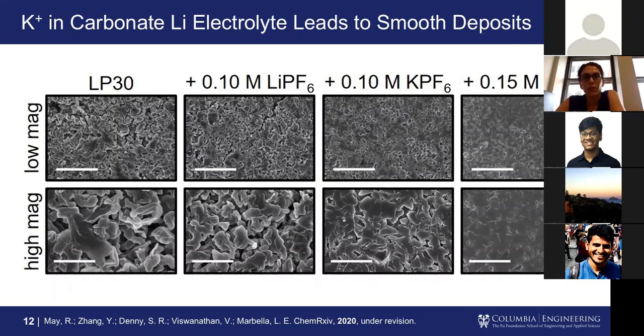So one of the first projects that we started to work on in my lab is, are there some type of additive that we can put into just a conventional commercial carbonate electrolyte that would give us smoother lithium deposition? Anything we could throw in there that would make the battery a little bit safer. This is showing these microstructures that grow on the surface of a lithium metal anode just depositing in a conventional commercial lithium ion battery electrolyte. That's what I'm showing here on the very far left.